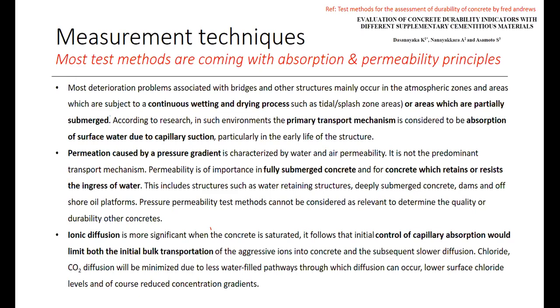But most research has proven that diffusion is not a big case, because diffusion also deals with absorption. Before starting the diffusion, it has to be absorbed into the porous media. Therefore, rather than analyzing the diffusion mechanism, it's much easier and much more accurate to identify the absorption properties or the capillary suction of the particular concrete element, rather than wasting time identifying the ionic diffusion. So those are the three key things that we want to focus on when we are dealing with the measurement techniques of durability.